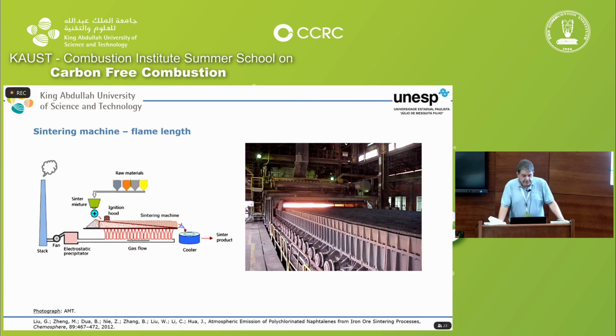You have, for example, a sintering machine. Sinter is one of the materials that go into the blast furnace. Besides agglomerating the mineral, it also contains some other materials that are necessary, like some carbonates. The sinter is mineral with about 5% of coke, or a very high carbon content coal, okay? So you have to ignite it.